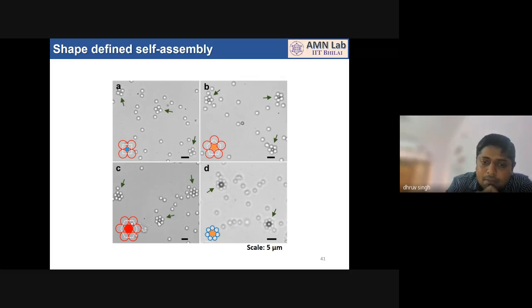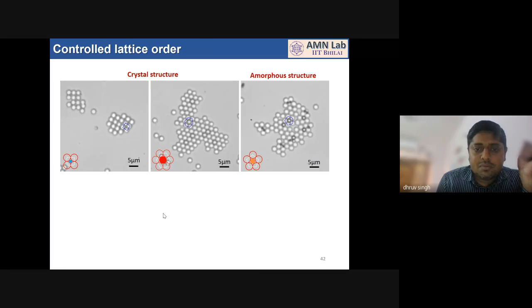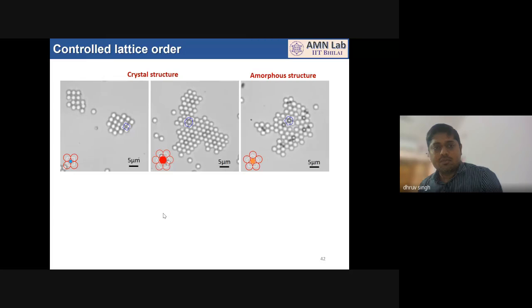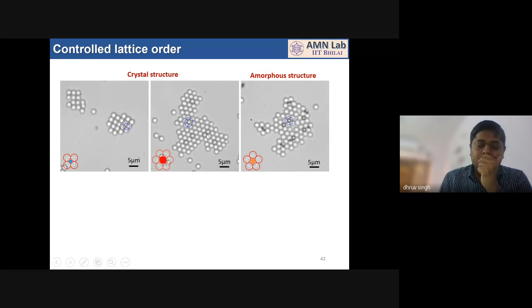Right now they are at the lower light intensity, so the interaction strength is low. So no particle can attach in the second layer. But if you increase the light intensity, this is the beauty of the dynamics here, then you can allow the particles to freely grow in size, like what you saw in the video before this. Then we got some interesting results, like we can form the assembly of different lattice orders, like the crystals of the square or hexagonal lattice order, or the amorphous assembly with a completely disordered state.